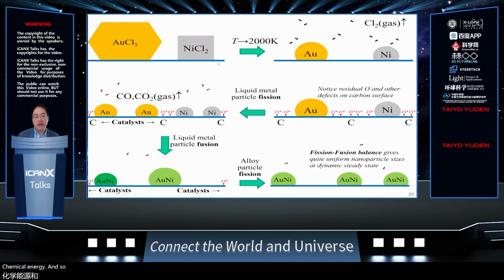And so our explanation of what happened was, initially you have these big micron-sized chlorides. And when we heat it up above 1,000 Celsius, these chlorides first leave. But then the metal finds that there is oxygen on the carbon surface, and it decides that by doing this fission, which means a big particle splits into two molten liquid particles, it can have more contact with this oxygen on the carbon support.